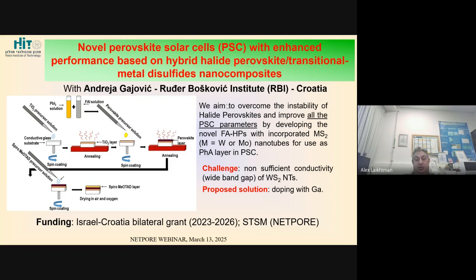The challenge is that WS2 nanotubes do not have sufficient conductivity, and plasma treatment does not improve the conductivity. The proposed solution is doping. Doping can be done chemically, for example, with rhenium, but it's a very complicated process where you should change the synthesis procedure, or by ion beams. So we suggested doping with gallium. I will briefly move to the gallium doping, and then I will come later to this research on perovskites.